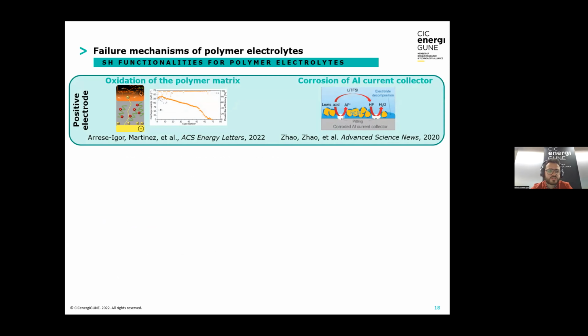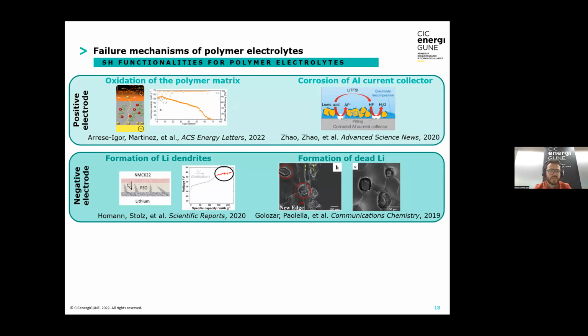So if we look at the problems we might find in this battery section, we have at the positive electrode the oxidation of the polymer matrix due to the use of high voltage active material, or the corrosion of the aluminum current collector, generally produced by the anion of the lithium salt. These are two issues that are usually not addressed with self-healing techniques, but that might have its field, its space for research. In the negative electrode, the formation of lithium dendrites or the formation of dead lithium. There are some works on this, but there is still an extensive field of research.